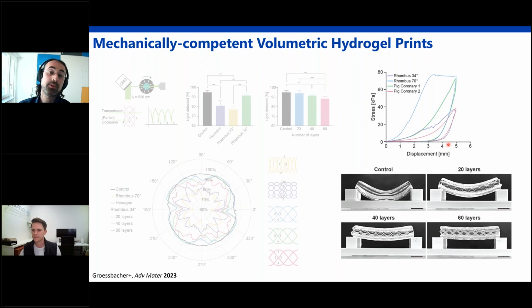Yeah, so we didn't observe any. We cultured the systems up to 2 weeks actually. We have also done it under flow in a perfusion bioreactor. We didn't experience any delamination. When we look at the failure mechanics of these constructs, when we bring them to failure in our mechanical test,